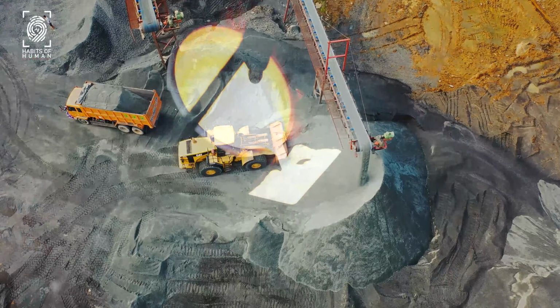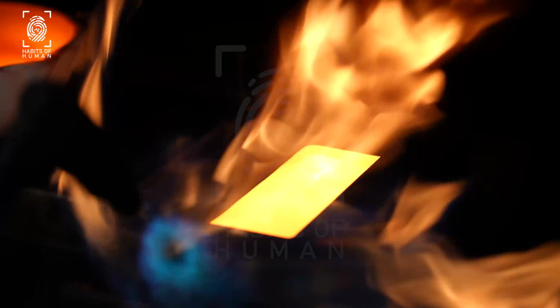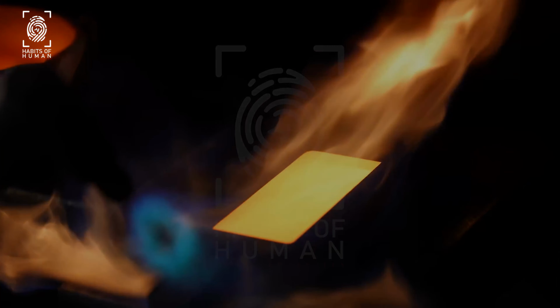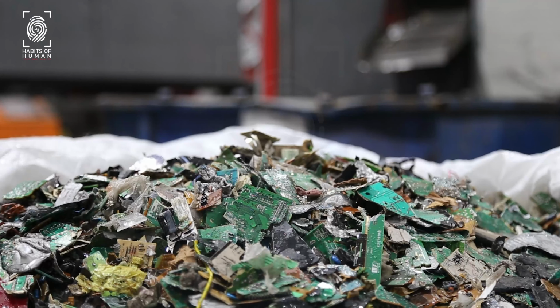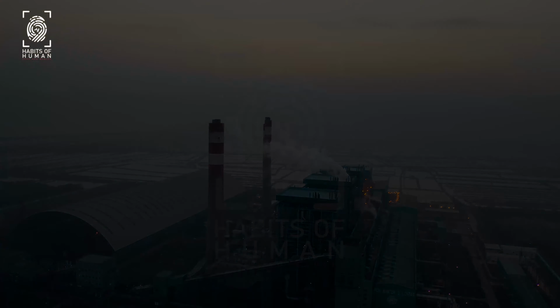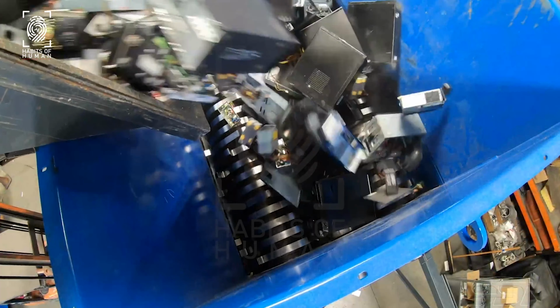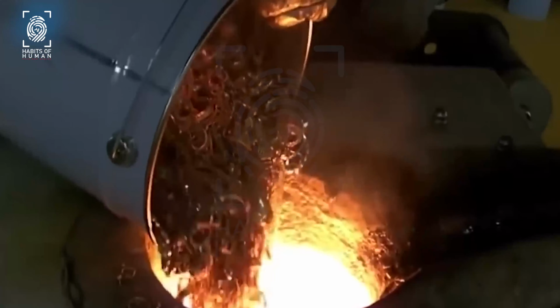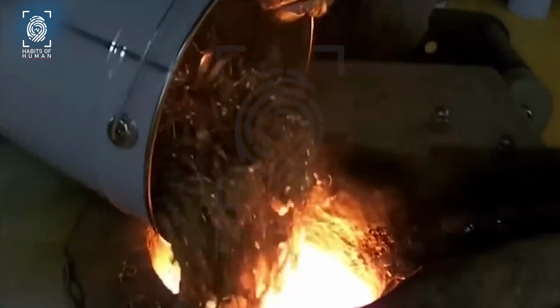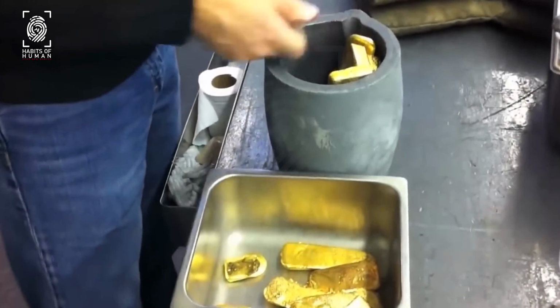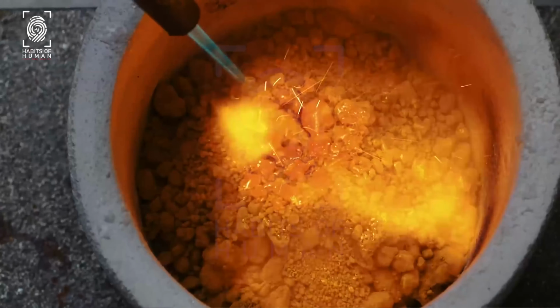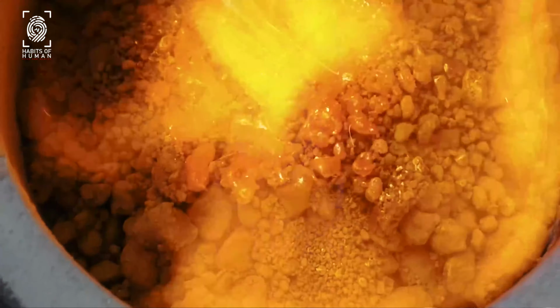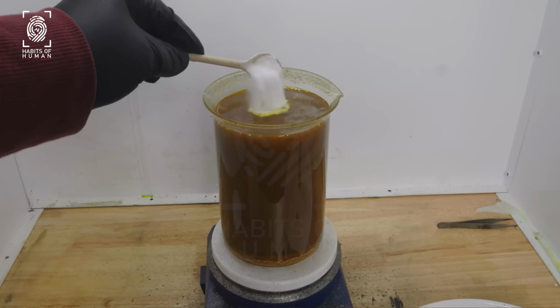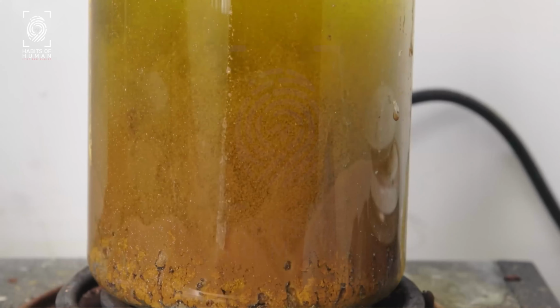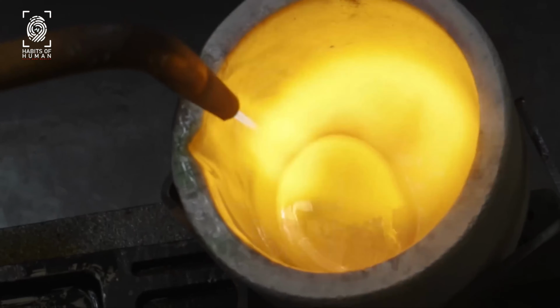Mining or recycling: gold can be obtained from gold-bearing ores through mining or from recycled materials, such as jewelry, electronic waste, or industrial byproducts. Crushing and grinding: if gold ore is used, it is typically crushed and ground into a fine powder to increase its surface area and facilitate the extraction process. Extraction: the gold is extracted from the crushed ore or recycled materials using various methods, such as cyanidation, which involves treating the material with a weak cyanide solution to dissolve the gold.